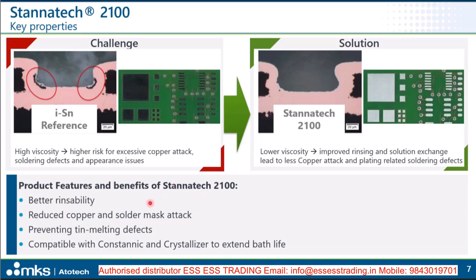One key piece of information which might also be important is that our immersion tin process comes along with auxiliary equipment like the Constannic and the crystallizer, which helps to extend the bath life of the immersion tin, so that you don't need to run the bath in feed and bleed, but can run the bath with constant performance with the same plating solution. And the new formulation is also compatible with the auxiliary equipment, so it can just be replaced as a drop-in in existing lines.